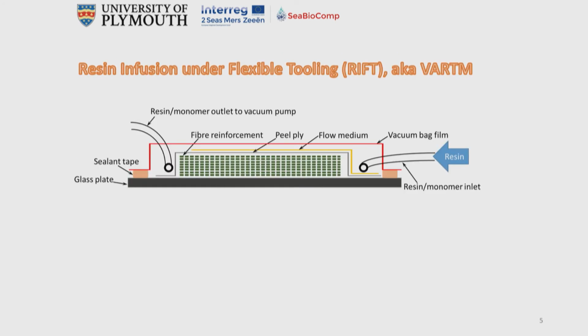In resin infusion under flexible tooling, also known as SCRIMP, VARTM, and about 50 other different abbreviations, we make a stack of fibres, cover it with release film, add a flow medium above that and then close it in a bag, and then flow the resin, which becomes a thermoset matrix, into the mesh to produce the composite by drawing a vacuum into the bag and allowing resin to flow down the pressure gradient.